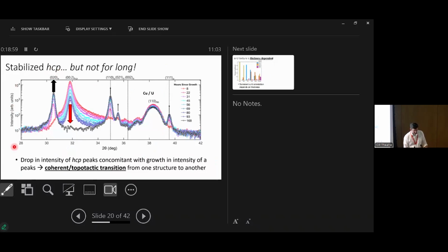This is an X-ray scan, so X-ray intensity versus angle, and a simple diffraction pattern. And this peak, let me focus on this peak. This is the hexagonal close packed peak. We saw clear evidence for it. But then within hours, days, weeks in some cases, that peak decayed and died away, and we lost the structure. But at the same time, we gained a peak, and this is the thermodynamically stable alpha orthorhombic peak. This is very weird. This doesn't usually happen.